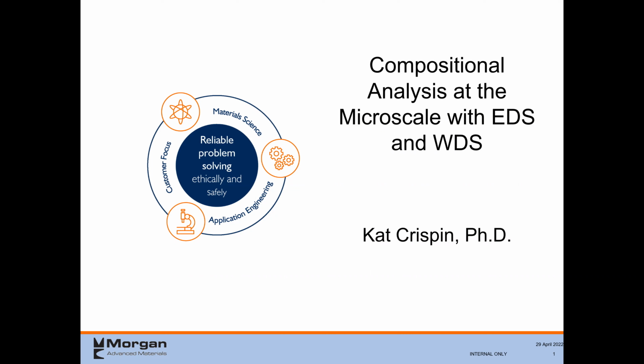EDS software in general has built-in standards. Those are fine for doing general ballpark ideas. However, if you need to get true quantitative analysis from EDS, you'd have to have standards that you know. There are companies out there that make standard blocks where they know exactly what the composition of the materials is, and you can analyze those in EDS. You analyze the standards, you tell it what the composition is, it stores it as a standard, and then it can reference that instead of the generic ones that are already built in. And you can get quantitative analysis that's done very well in EDS if you're careful about doing your standardization.